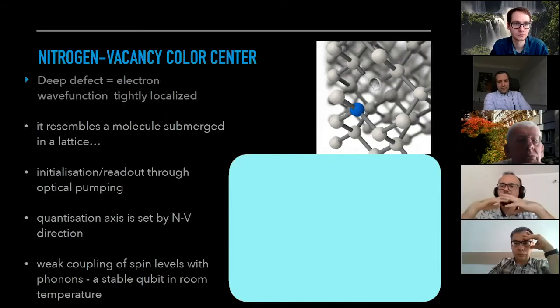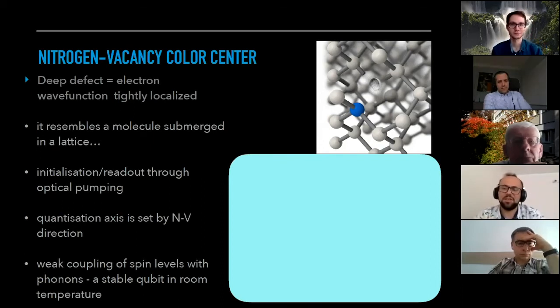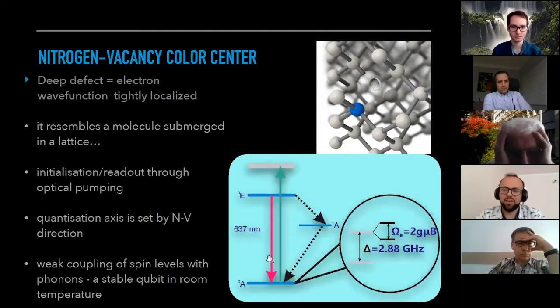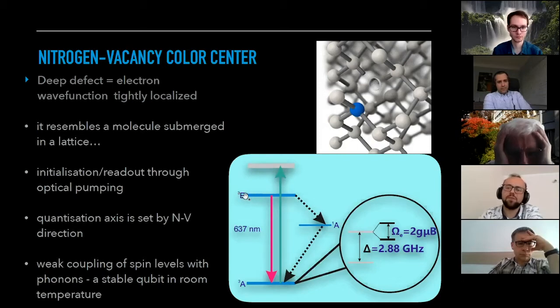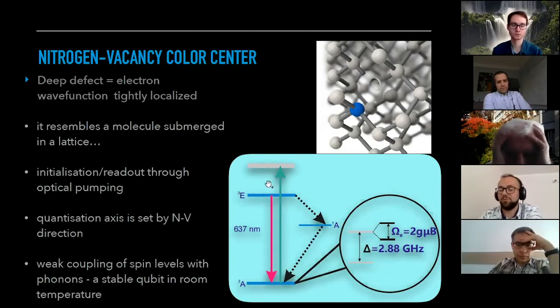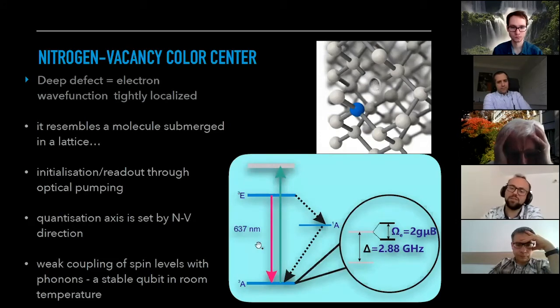The free electron pair of nitrogen, three electrons from nearest neighbor carbons, and also an electron coming from the lattice creates a sort of molecule diluted in the diamond, which has energy levels lying between the valence and conduction band of diamond. It is extremely lucky that we can control this — the difference between ground and excited state corresponds to visible laser. Above the excited triplet state we have a continuum of phonon sideband, which means for initialization we can use a different wavelength than for readout.